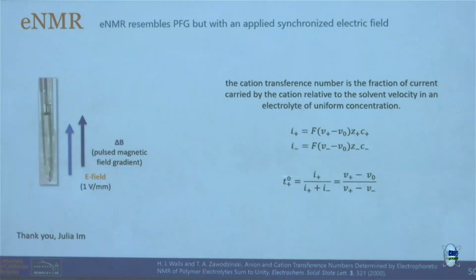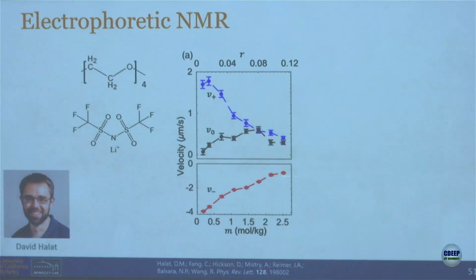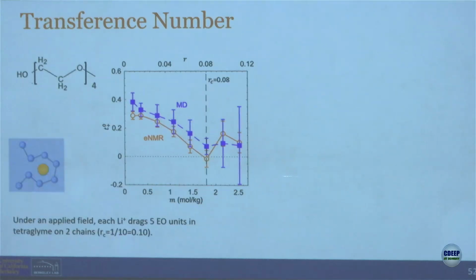And because NMR is such a beautiful experiment, the error bars come way down. Okay? And then these are the measurements of the velocities in microns per second. As a function of salt concentration, you can see the R on the top. In the same solvent, but in a solvent called tetraglime, which is a PEO chain with 4 repeat units. And that's just because it's hard to stuff PEO in the NMR tube without breaking it. Okay? So we use an analog to get our results accurate. And this is the data.